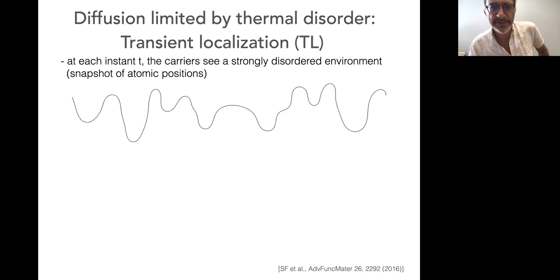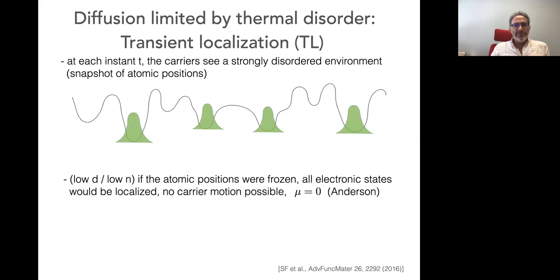So what is happening here is that if you take a snapshot of your material at some instant in time, the carrier will see a very disordered environment. So if this environment was just frozen, then we know how to solve a Hamiltonian with static disorder, and we know that the wave functions will localize at the minima of this potential. Now, localized means that nothing is moving, and so the mobility would be strictly equal to 0.